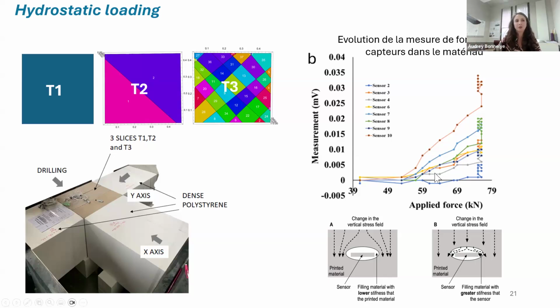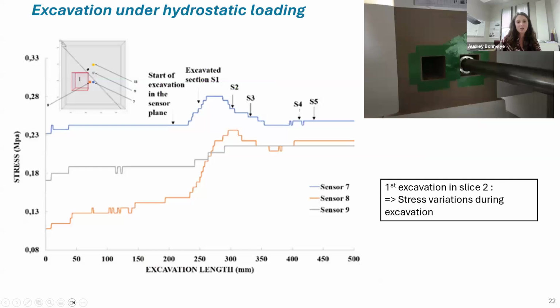And we see that when we load it hydrostatically, our sensors are responding. We are not fully sure yet of what we do measure, because there is a very complex interplay between our samples, which are very soft, the sensor, and how to insert the sensor directly inside of the material. But we see that we have an evolution, and actually when we start drilling in the sample, here you have the evolution of the excavation length. Here it's the evolution of the stress measurement inside of the second slice.